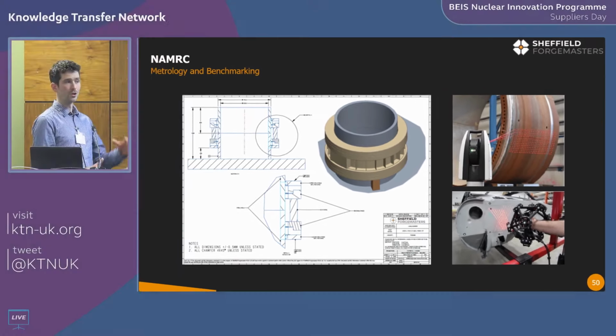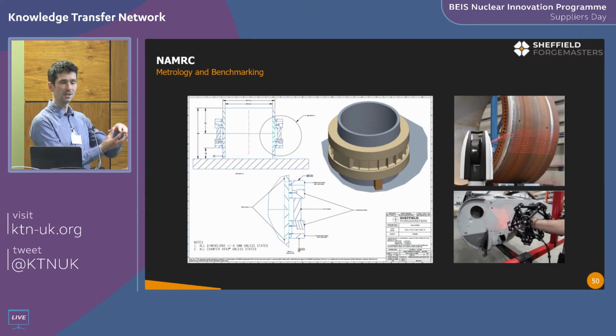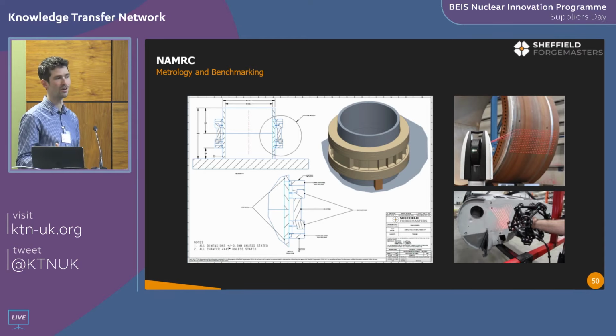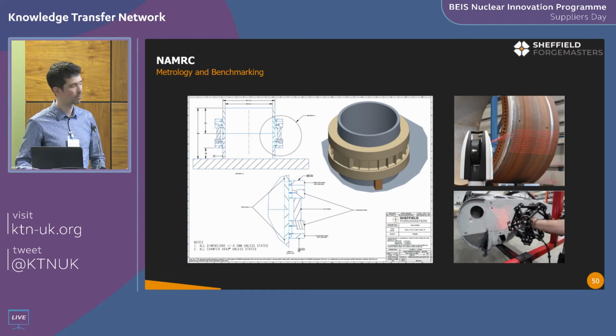With nuclear MRC, the present work's concentrated on metrology, so basically we've got a load of rings and shells to stack together, and this thing's going to weigh up to 60 tons. So putting those concentrically on top of each other and manipulating them is quite tricky. You need quite a lot of heavy kit, and if they're slightly out, you can't really push them in quite easily. So we need metrology methods that will give us appropriate distance that we can have a standoff, but control quite precisely accurate placement of these assemblies.